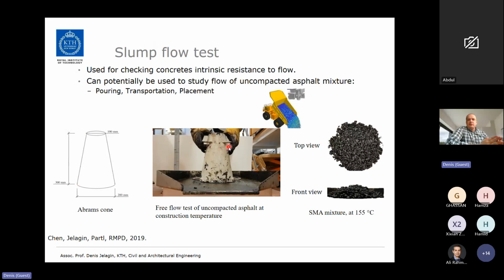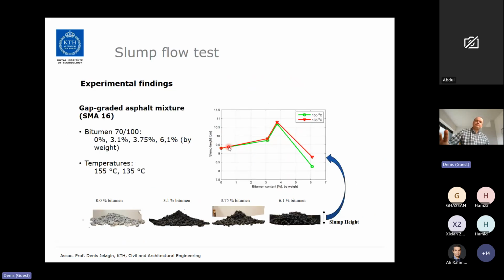Here we really aimed for something simple, yet being able to capture flow characteristics of completely unconfined asphalt mixture. So situation representative for pouring, transportation, mixture placement, etc., etc. And then this test was early on aimed to be used to validate and calibrate discrete element models for those situations. And this is how example of experimental findings look like. Here we look at SMA 16 with different binder content.